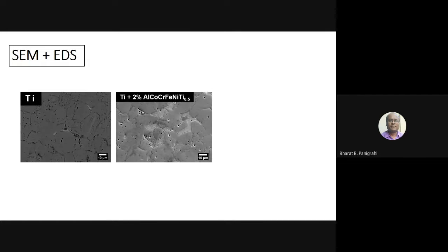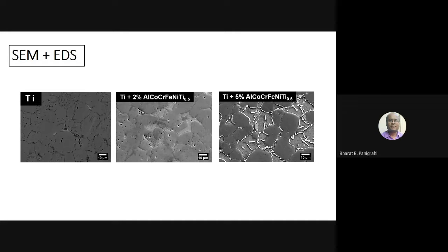If you look at the microstructure, this is the titanium microstructure. The moment you have the high entropy alloy phase, it has formed nice precipitates, and these are very hard phases. These hard phases lead to a jump in the hardness as well as strength of this particular composite. So you have a plain microstructure versus a microstructure which has a lot of precipitates, and these are very hard precipitates having a high entropy phase in them, and you are able to increase the strength and hardness significantly.